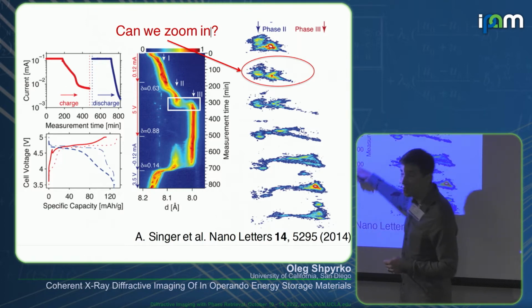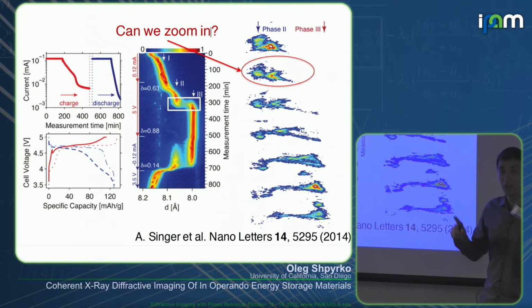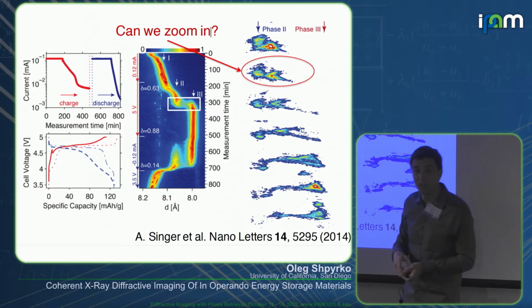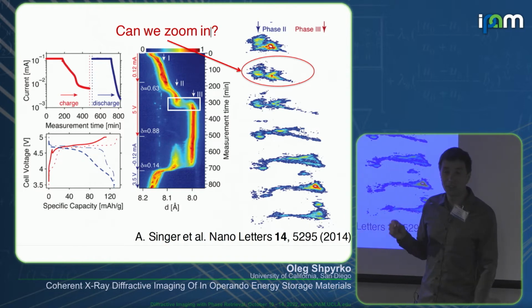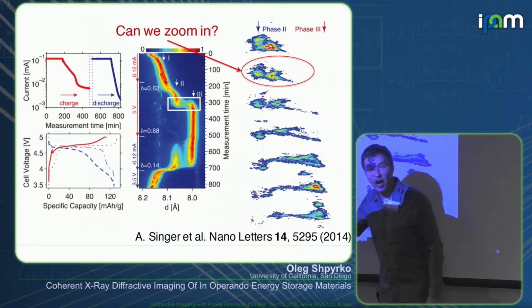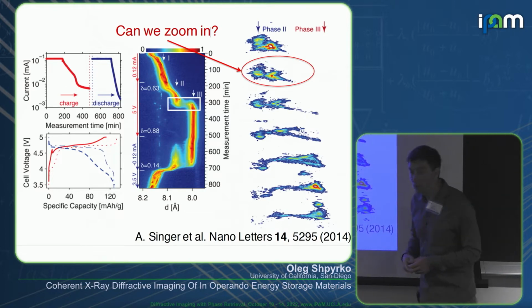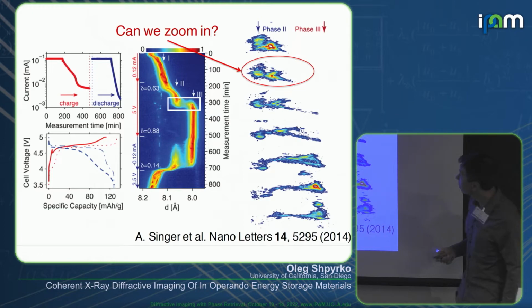There is hysteresis, and I would argue that none of my colleagues, and even I, fully understand the source of hysteresis. But obviously, anytime you have hysteresis in a system, it means that your battery actually knows whether it's being charged or discharged at the same voltage state, the same charge state, which means that it has a little bit of memory, right? And that means that there are probably some sort of defects that guide that memory. How else would you violate the thermodynamic equilibrium if you didn't have some sort of defects guiding it?